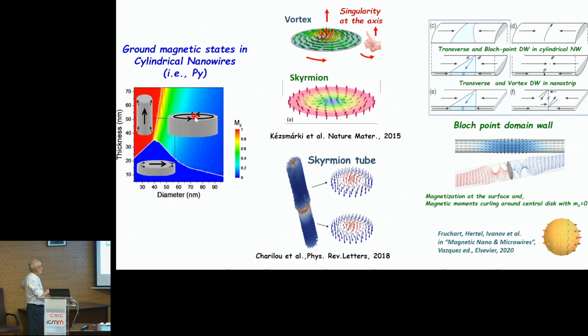In a vortex, the magnetic moments are circumferentially aligned. You see here also, but in the very axis, because of the exchange coupling, the magnetic moment has to be perpendicular to the plane of the vortex. More recently, as you know, skyrmions have become very fashionable. In fact, a skyrmion is a kind of vortex, but more complex, because in the very center we have magnetization pointing down, for example, and at the surface, magnetic moments are up oriented. So we have a transition in this area. Most of the work has been done in planar, thin films. So a skyrmion is nearly a dot, having this distribution of magnetic moments.